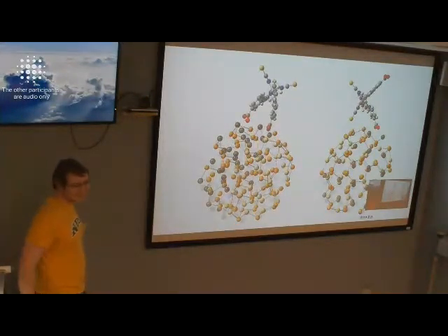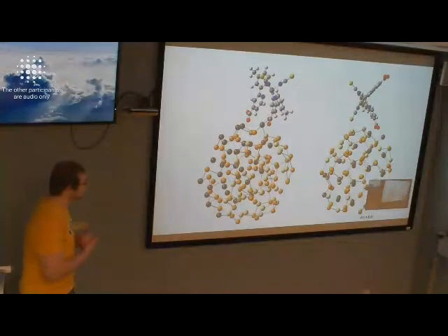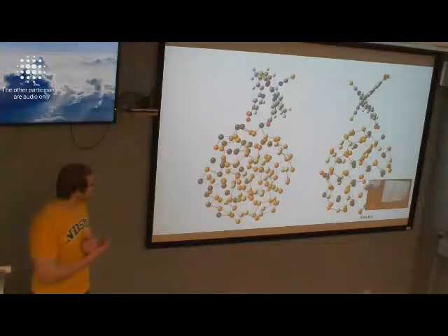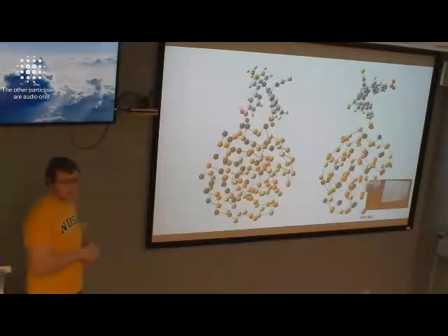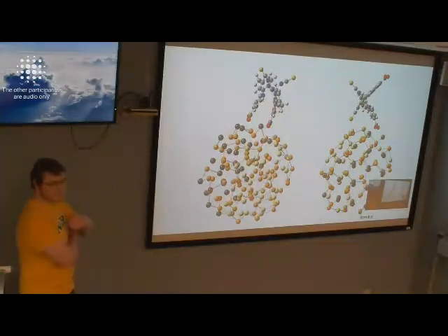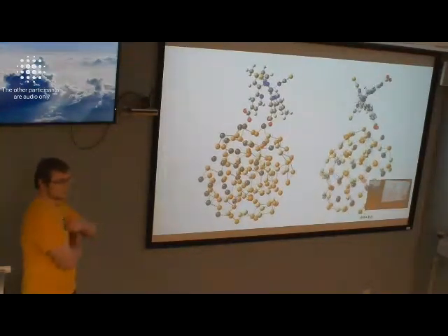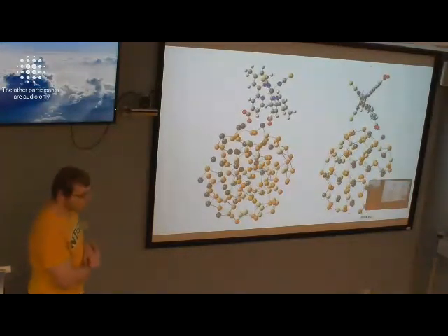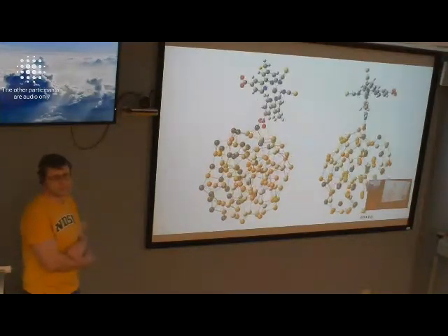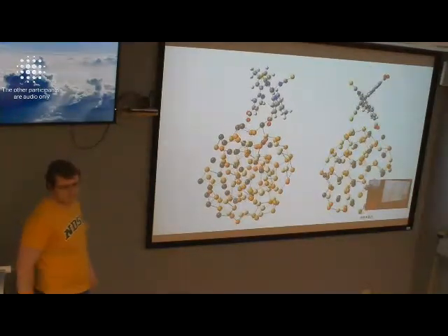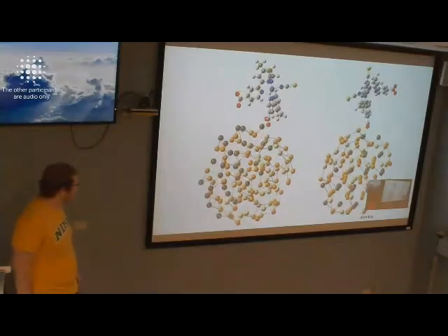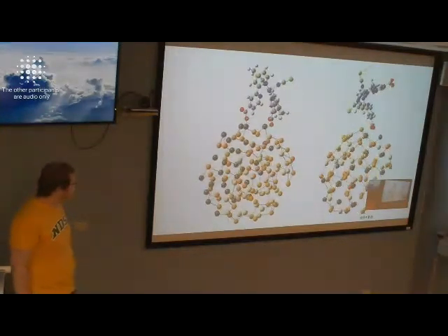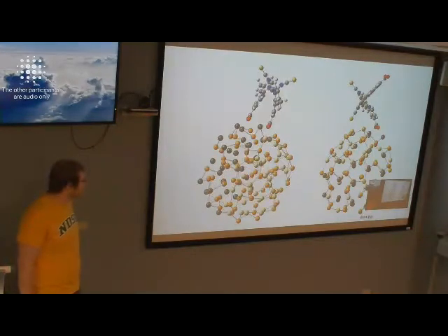But again, this is a very polar molecule with a huge dipole. We calculated the dipole of something more than 100 debye for these molecules. For the cadmium selenide surface it's around 20, and for lead it's something like 5 or 10, I don't remember. So it's a huge dipole, and when you interact with the surface, you drastically change the interaction and the dipole. It's very natural to expect that even the atoms far away from the binding site should feel this and maybe rearrange, because you're really changing the dipole of the entire system.